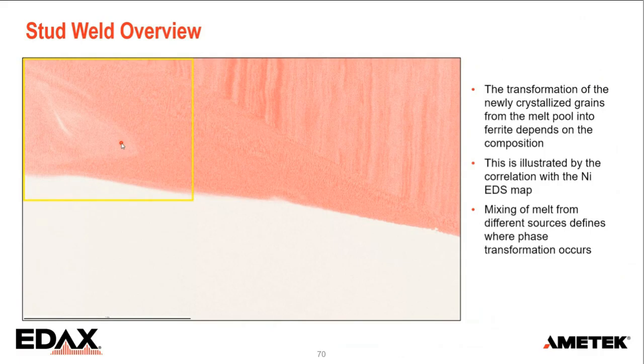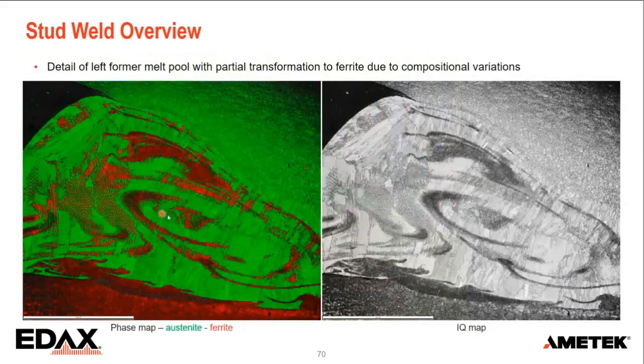What happened when the stud was pushed into the melt. And when we zoom into that, we can see exactly what happens. The areas where we had low nickel actually transform into this ferrite, these red grains. And they're so small, that's why the pattern quality is much poorer than those nice large austenite grains.